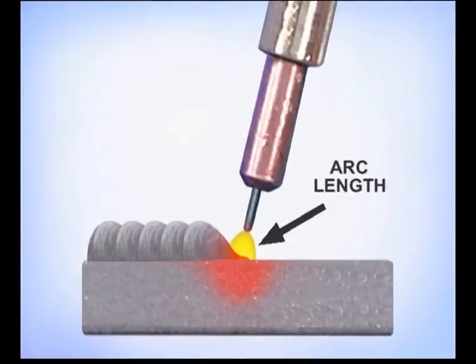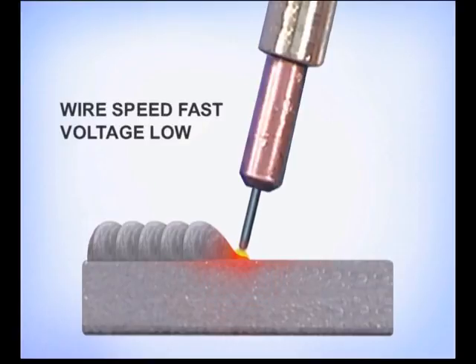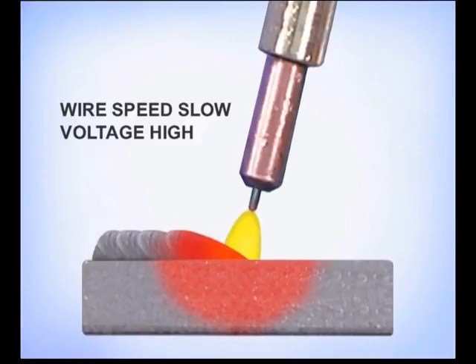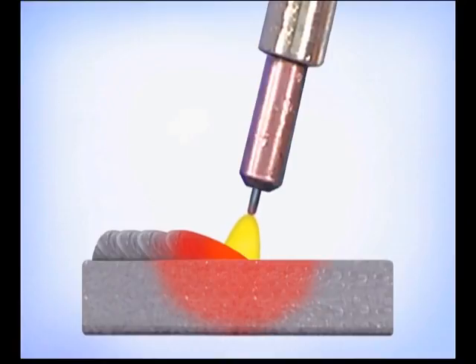Watch the tip of the wire, looking directly at the arc length. If the wire speed is too fast for the voltage, the wire will run into the puddle, kind of exploding and causing excessive weld spatter. If the wire speed is too slow, the arc length is increased, causing the puddle to widen and flattening the weld buildup. The voltage and wire speed should be tuned for a short arc length, right above the surface of the metal.